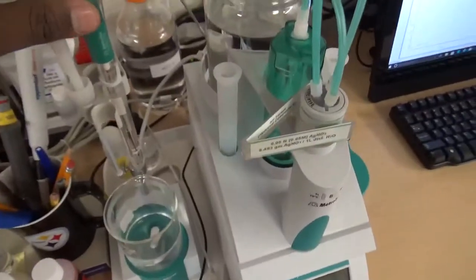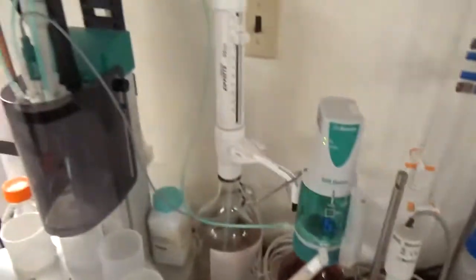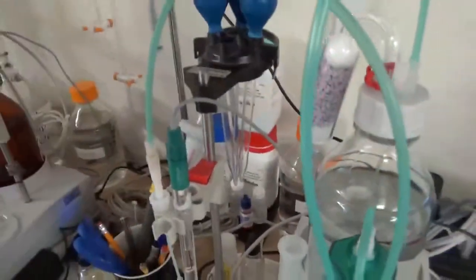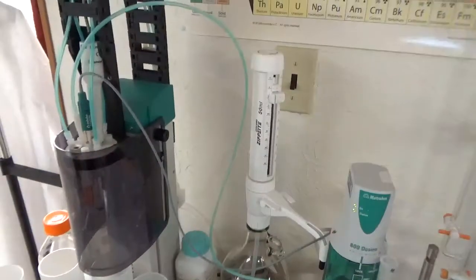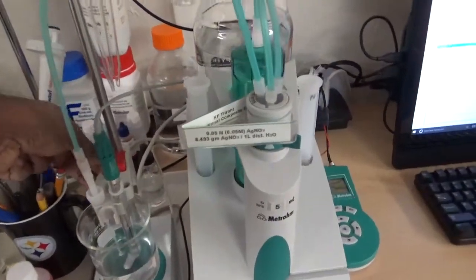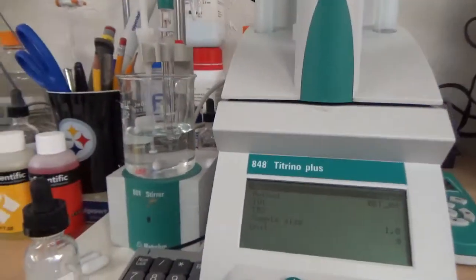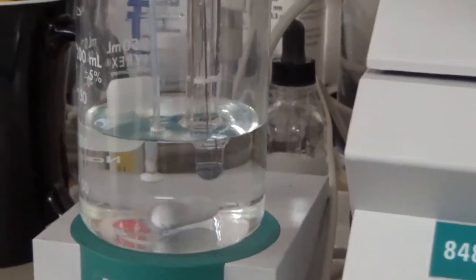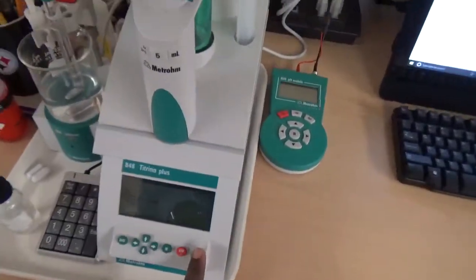I have the pH electrode as opposed to the metal electrode, the silver electrode that we used for chloride titration. Here we are using a pH electrode. The metal electrode is stored in potassium nitrate storage solution, whereas the pH electrode is stored in potassium chloride storage solution. So we have the burette and the electrode. We simply dip them into the solution, making sure they are not touching the stirrer. The tip of the pH electrode shouldn't touch that stirrer, and that's why we have this stopper, so it doesn't go all the way down. And once it's set up, everything is ready, you just press go.